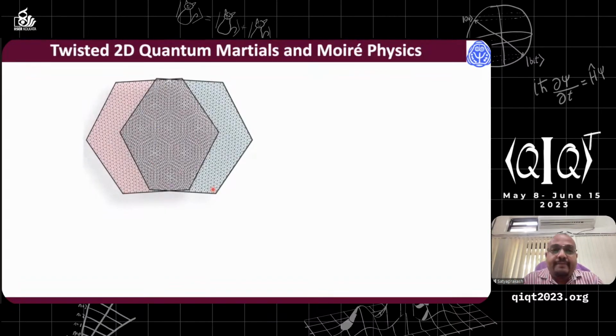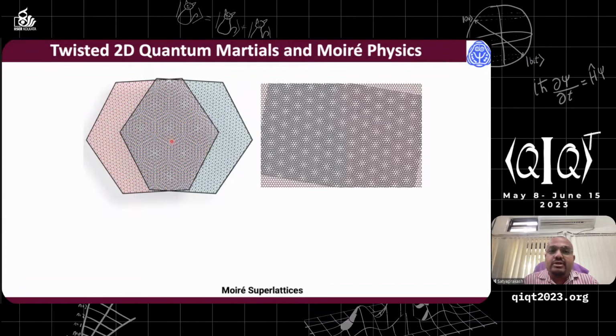Another emerging interesting area is twisted quantum material. As you can see here, when two layers of graphene are twisted with a small angle, you can see a new periodic pattern emerge. This type of pattern is called the Moiré superlattice, and we know electrons love periodicity. Whenever a new periodicity emerges, electrons show new character, either in the transport property or in the band structure. So by changing the twisting angle between the two 2D materials, one can get an artificial new system having different periodicity. This is a very important topic of research nowadays.